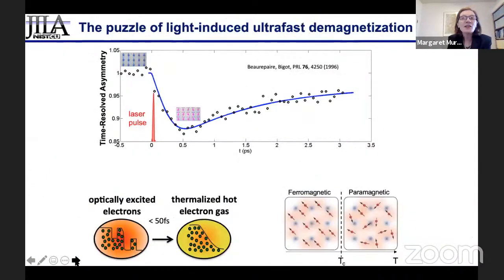And the other very interesting thing we found is that one can actually map new quantum phases, phase transitions, new excited states, and one can really think about a femtosecond laser as a very delicate manipulator of materials, not something that puts everything into a very far out of equilibrium state, but instead very delicately manipulates the electron-phonon and phonon-phonon interactions. So I like this. And one system where we were able to discover a lot of surprises is in